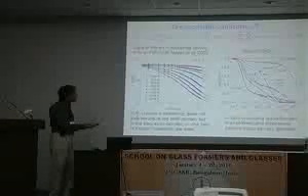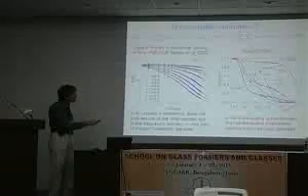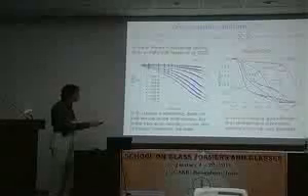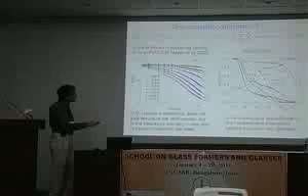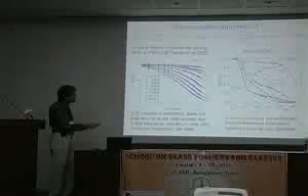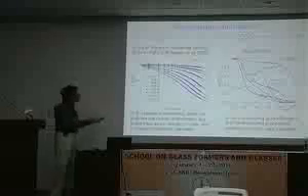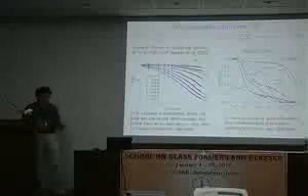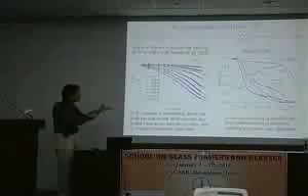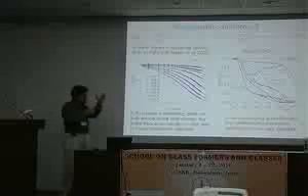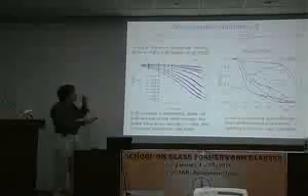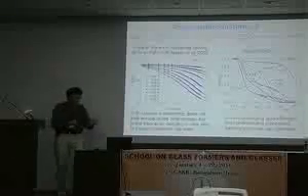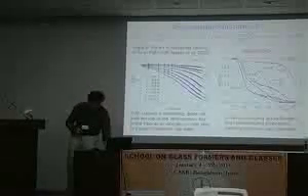However, if you go at larger distances, that is to say smaller wave vector, then you see that this difference can be orders of magnitude, and in these ion-conducting glass formers, for example, the self and collective functions behave in very, very different ways. Again, I don't want to go into the details, but just want to convince you these functions are interesting, and especially for glass physics, they really can teach you something about the mechanism of the transport of the system.